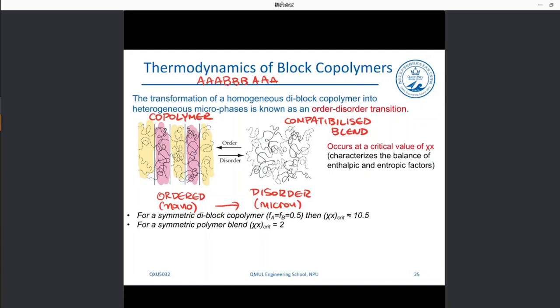Okay, this order to disorder transition occurs at the critical value of the product χN, the Flory-Huggins parameter times the degree of polymerization. It's characterized by the balance of enthalpic and entropic contributions. It's not possible to evaluate that in the context of this course, but simply I'll tell you that for a symmetric diblock copolymer, meaning that we have equal amounts of A and B, this critical value, which we will see in a bit is called the weak segregation limit, is 10.5.